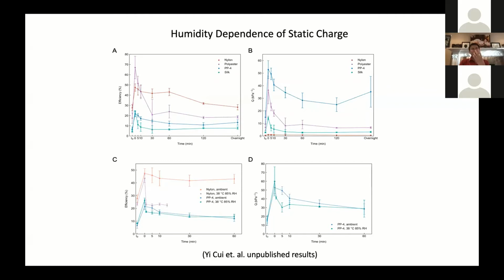It's a very humid condition. Under the humid condition, we discovered nothing else works except polypropylene. Nylon will lose static charge fast. Polyester will lose static charge fast. Silk will lose electrostatic charge fast. So C and D right here, and this plot right there is polypropylene. Only polypropylene, PP, can survive.